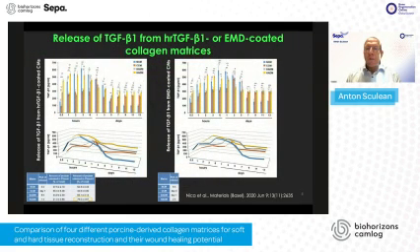However, if we look at the different peaks, you can see that the growth factors are released from all matrices. What we observed, if we compare the 4 different matrices, as you can see in the bottom left small table, is that the hydrated acellular dermal matrix releases a higher amount of proteins in a so-called phase 2, and this amount was roughly about 80%.